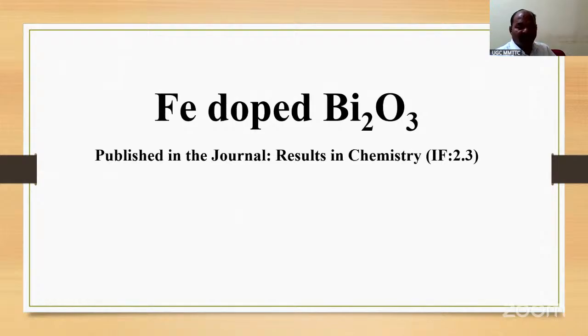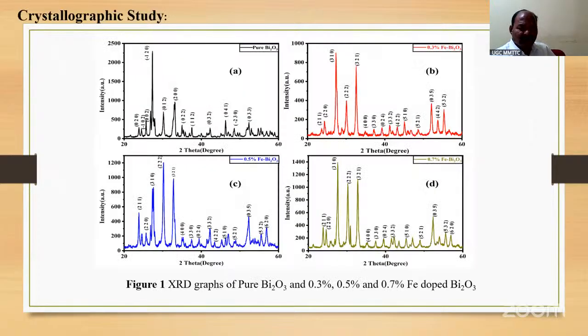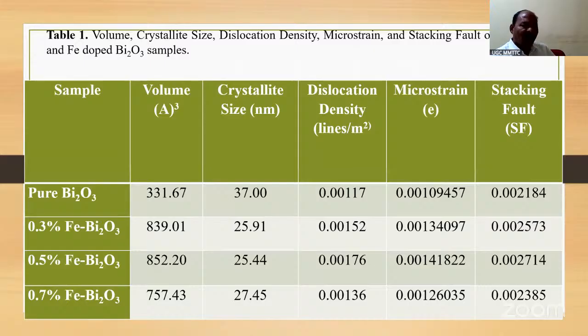So here the iron doped bismuth oxide, and the paper was published in Results in Chemistry. Its impact factor was 2.3. So this is the crystallographic study of the synthesized pure bismuth oxide materials, and now here you see the lattice parameters and all these. This is the X-ray diffraction. These are the patterns. Okay, and this is the volume, crystallite size, dislocation density, microstrain, and stacking fault of pristine and iron doped bismuth oxide samples.